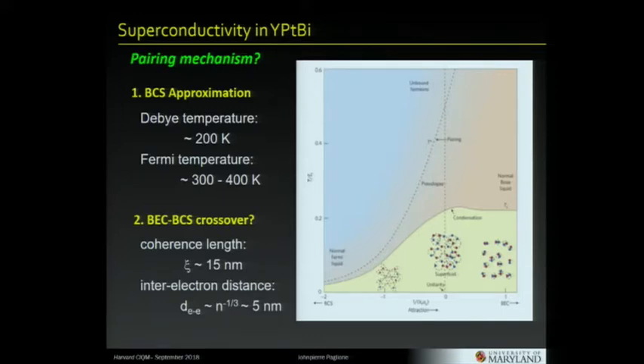This is interestingly somewhere near this crossover. I wouldn't say it's crossed over already, but it's close enough that it makes life difficult in trying to understand what kind of superconductor this is. Another part that's very hard to understand is that the Fermi temperature itself is on the order of room temperature, just based on the carrier density. That means that it's near the Debye temperature. And if you've done any course on superconductivity, at some point early on you go to what's called the Froelich approximation, which means that you take this limit where Fermi temperature is infinite compared to Debye temperature, and then you carry on in the calculation. If you can't do that, then you can't do BCS approximation. So that's already some theoretical limit.